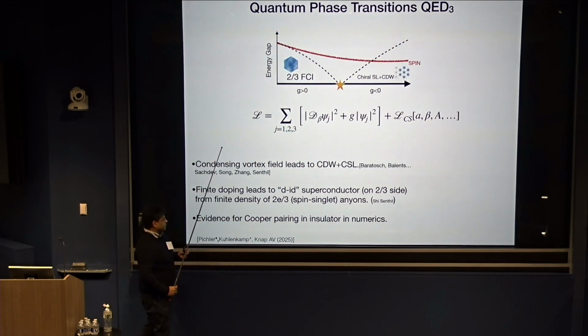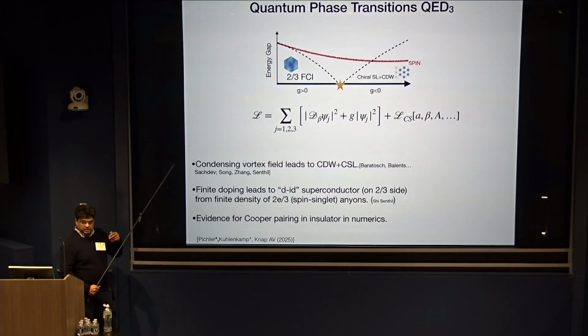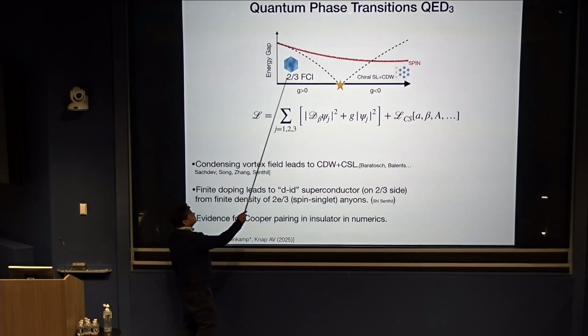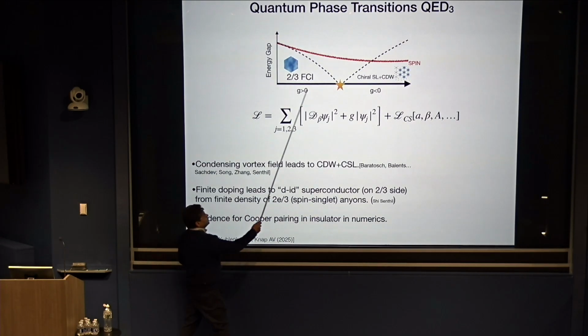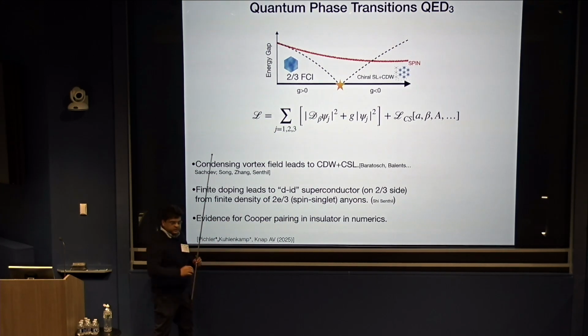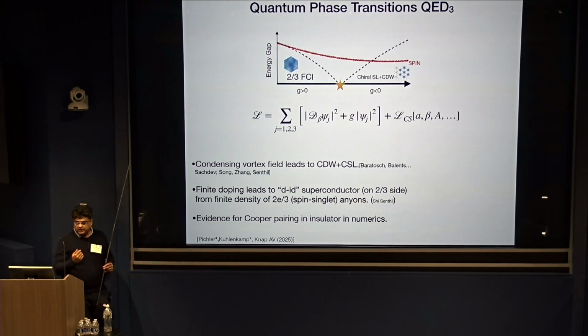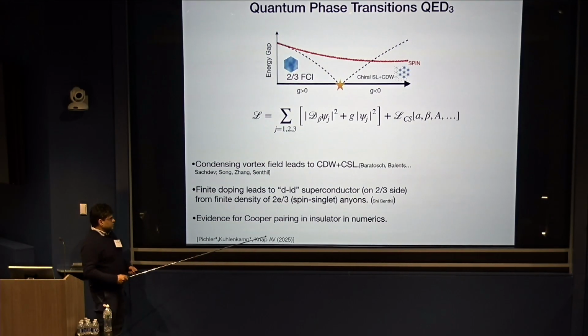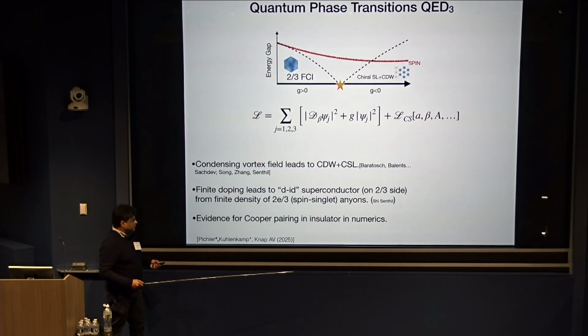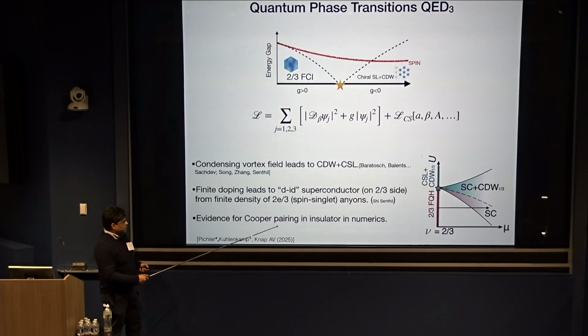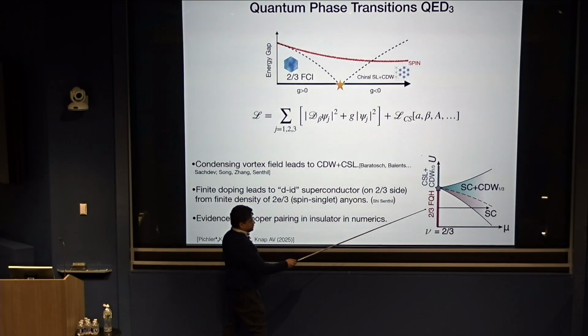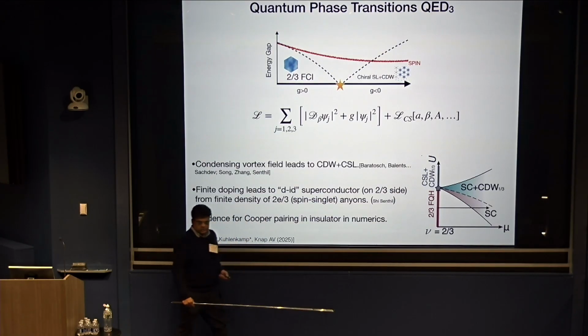And then if you dope that in, you expect to get superconductivity by very similar arguments. Okay, now we don't quite have the finite doping numerics in this case. We do for the other one, and Donna Sheng and Leon also had a paper on that. But we can sit in the insulator and look at signatures of whether the gap states are like Cooper pairs or like single electrons. Okay, and you do see that the correlation length for spin is exponentially decaying, or fairly short range correlated, giving evidence for this scenario that doping this will end up going into the superconductor.